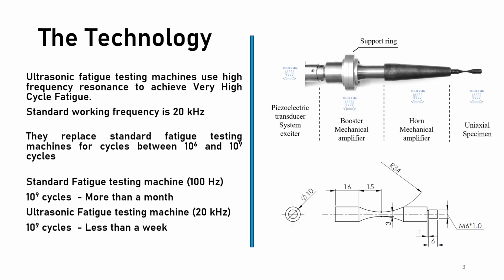Now in this study we have applied ultrasonic fatigue testing machines as a way to achieve the very high cycle fatigue regime. This regime occurs between 10 to the power of 6 to 10 to the power of 9 cycles. In order to reach such a high number of cycles, a piezoelectric transducer is used to excite resonance to a specific setup and the testing specimen.